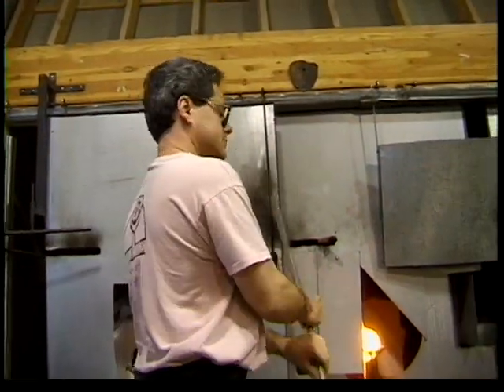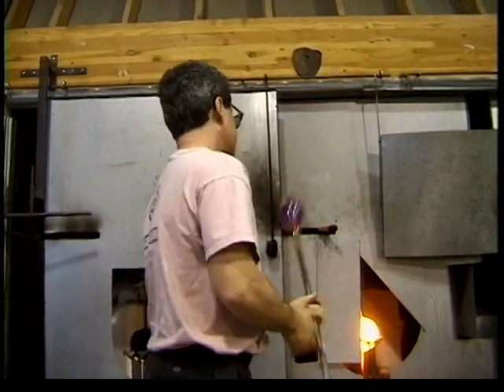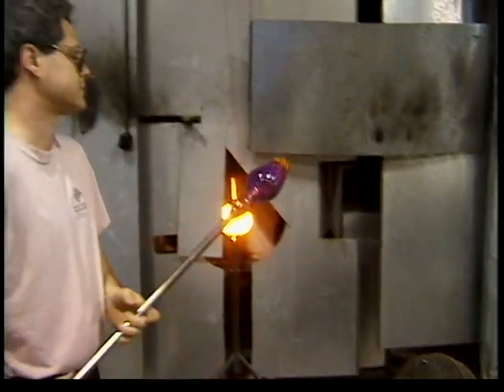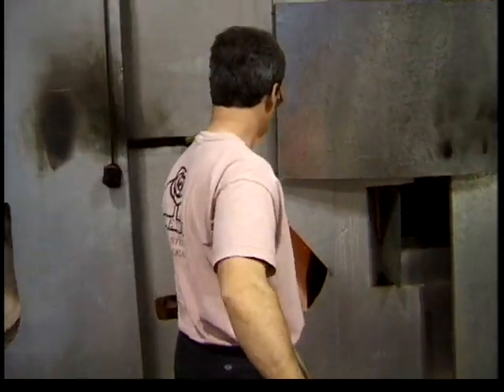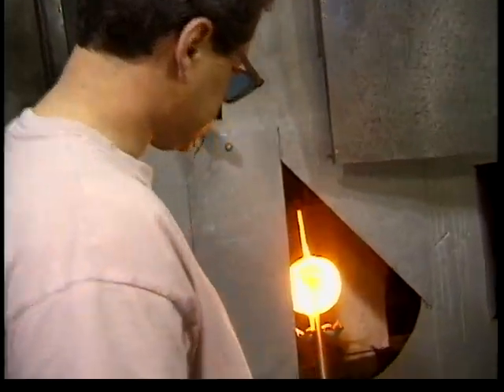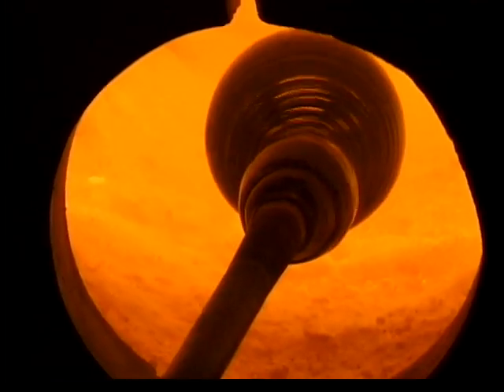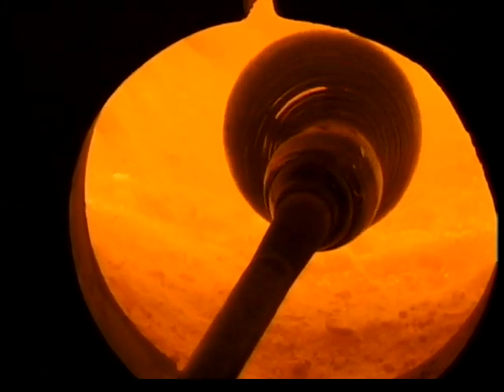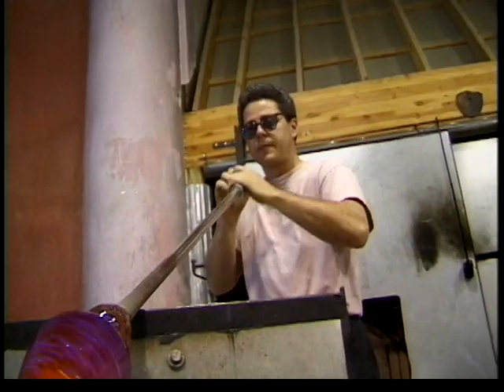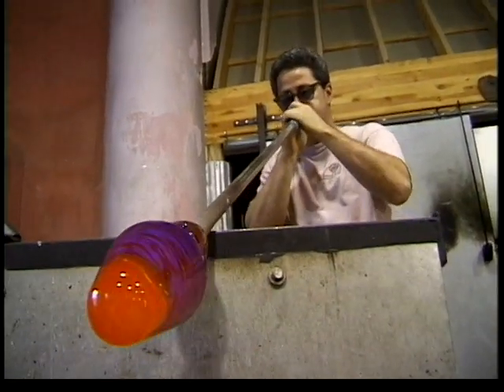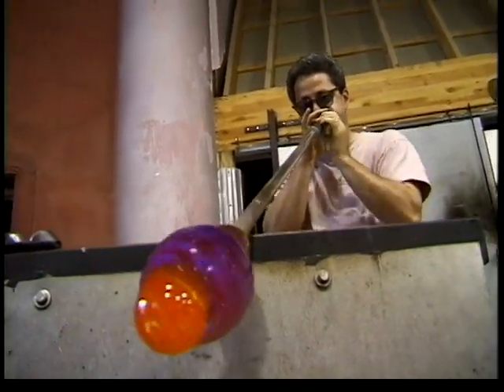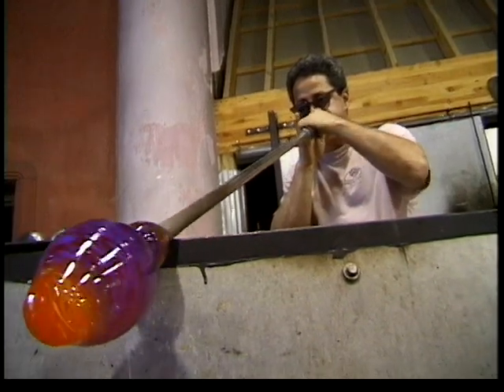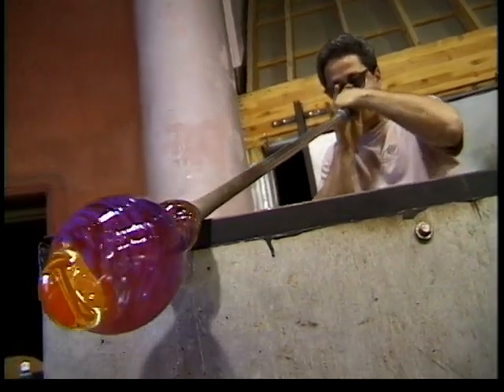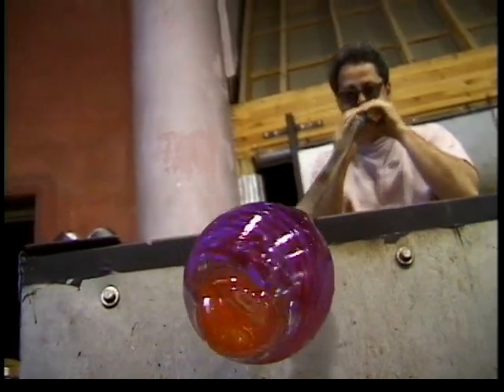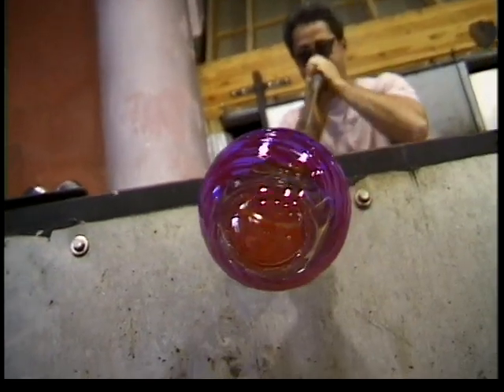To place a bubble into the piece, what you do is the glass has to be a certain temperature. If the glass is too cold, a bubble can't blow out. If the glass is too hot, the bubble will blow out very fast, and you won't be able to control it. So what you want to do is have the glass at a certain temperature, and then you lightly breathe air through the pipe, and that will expand at the bottom of the pipe where the glass is and give you a bubble into the glass.